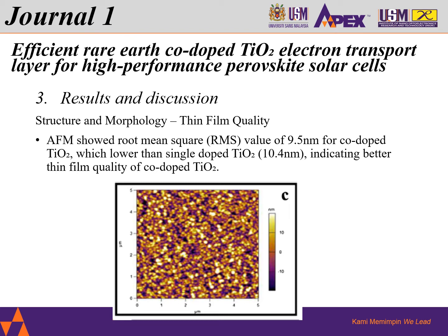Comparing the thin film quality with the doped and without doped TiO2, a very small RMS value is observed on the co-doped one. So this shows that the co-doped TiO2 ETLs have a better thin film quality compared to the one without doping.